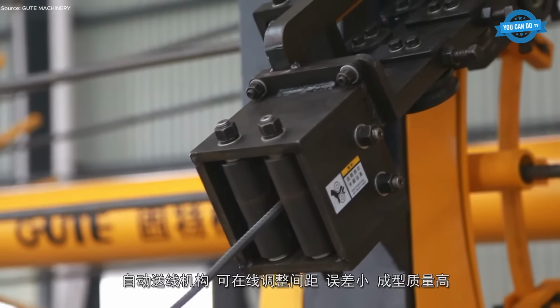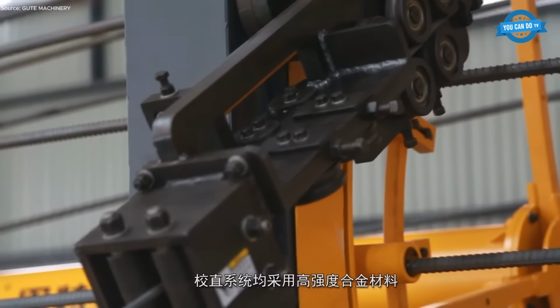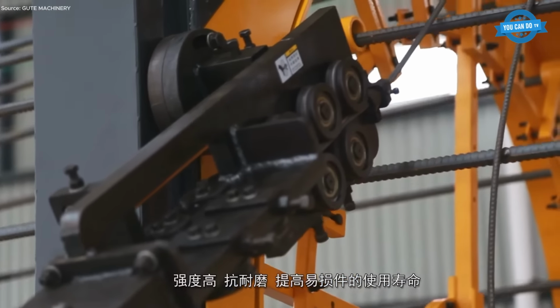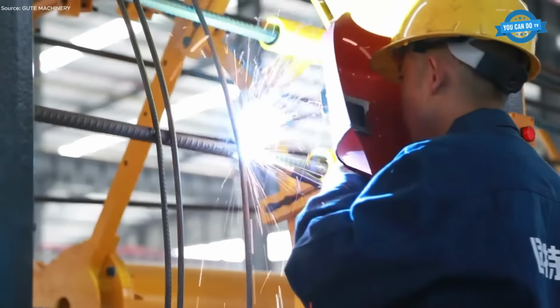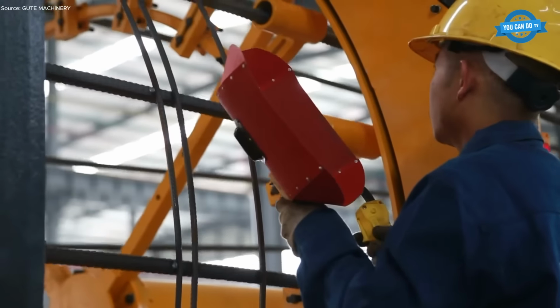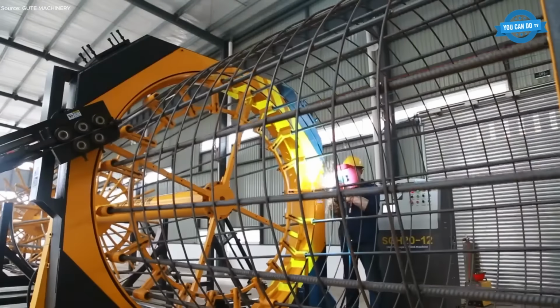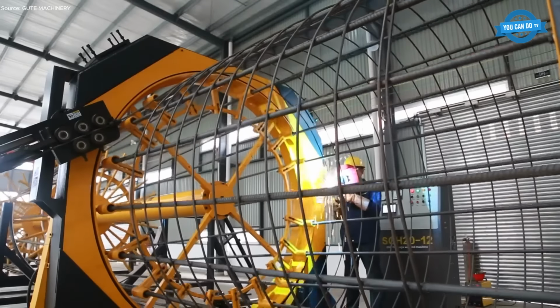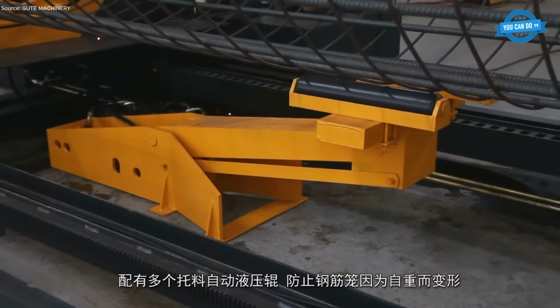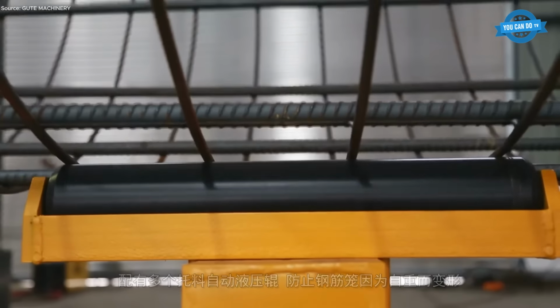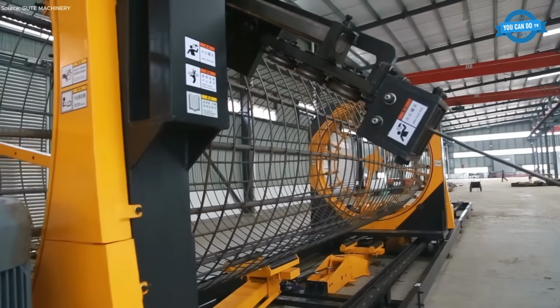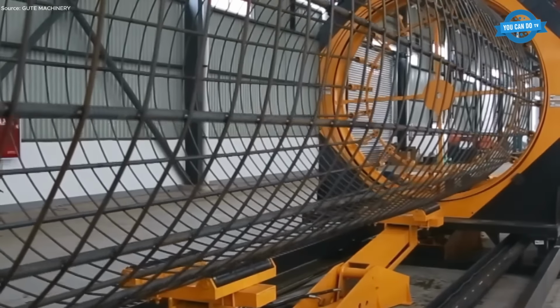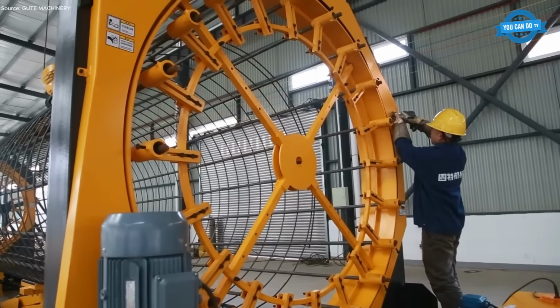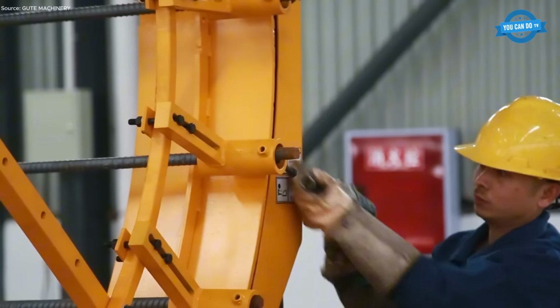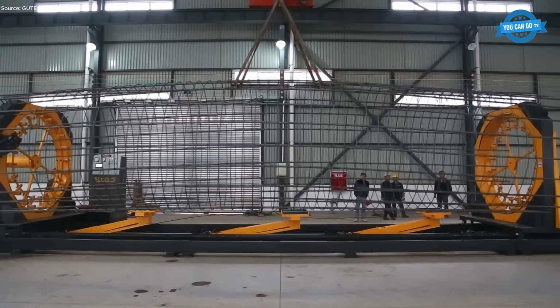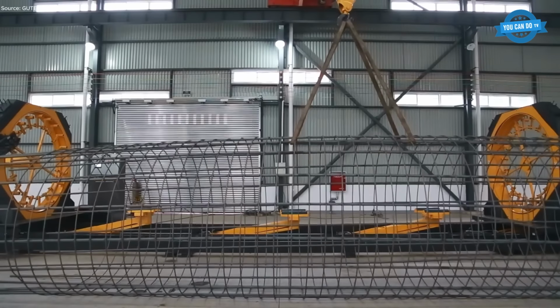An automated wire feeding mechanism controls the spiral reinforcement spacing, enabling precise online adjustment with minimal pitch error and high forming accuracy. The straightening system is manufactured from high-strength alloy materials, providing excellent wear resistance and extended service life for critical components. Multiple hydraulic support rollers hold and stabilize the reinforcement cage during production, preventing deformation caused by the cage's own weight. A variable frequency-controlled cage pulling mechanism ensures smooth movement and high positioning accuracy throughout the welding process.